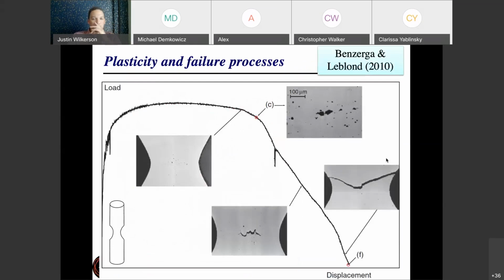Okay, and so we already touched upon this, but this is just showing a typical quasi-static load displacement curve where you load elastically, you hit a yield point, you get some hardening, you come to an ultimate tensile strength of the material. When I'm at the ultimate tensile strength of the material under uniaxial loading, that is all associated with necking and plasticity of the material. It's not even any damage at this point. So ultimate tensile strength should really not be thought of as having anything to do with failure or fracture.